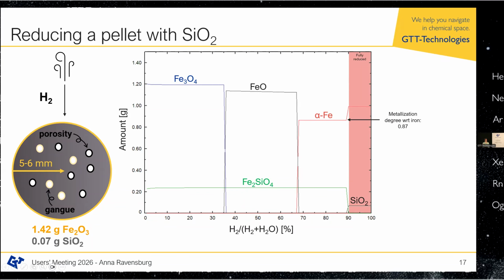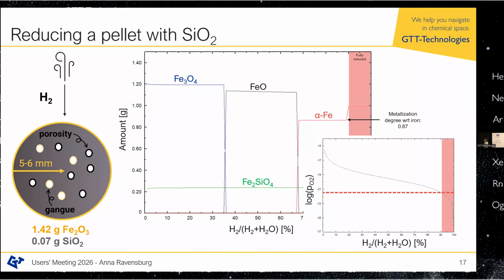And this is quite important because this is the real value of how much water vapor I can have in my furnace. Again, this depends on the oxygen partial pressure, which is plotted here. So it's somehow the logarithm of the oxygen partial pressure is somehow minus 21.4 for when I reach full conversion of iron.